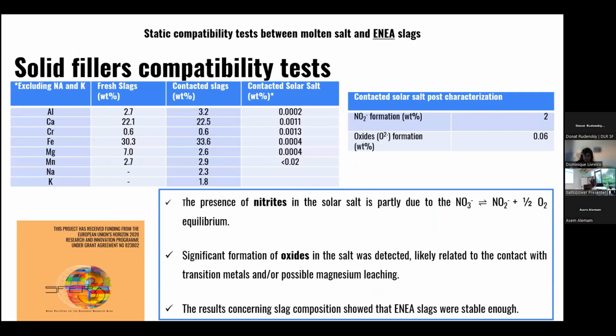These are the compatibility tests between molten salt, that is solar salt, and ENEA slags. I reported the elemental analysis for fresh slags, the slags in contact with the salt, and of the salt after the experimental campaign. We can state that the presence of nitrites in the solar salt is due to this equilibrium, that there is a formation of the oxide, but is related to the contact with the transition metal and possible magnesium leaching. So the overall result concerning slag composition showed that ENEA slags were stable enough to be used as storage materials.